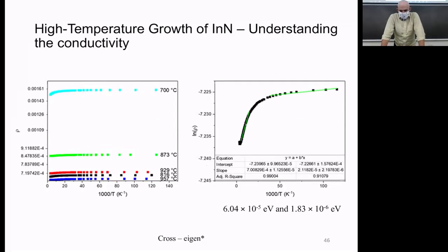Well, one of the first things I did was I plotted the log of the resistivity as a function of temperature, or inverse temperature. And what this does is it lets me know when electrons become available to transition. Because they are locked in energy states, as I increase the temperature, they can be, quote unquote, unlocked. They can start to move from a state where they're pretty much bound to their atom to a state where they start to be able to move a little bit easier. And I can find that value by following these 2 lines right here.